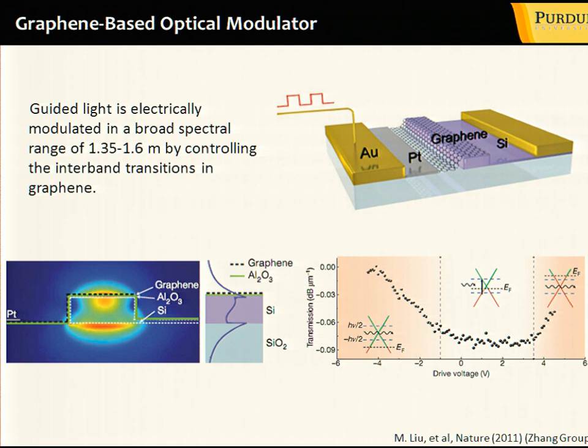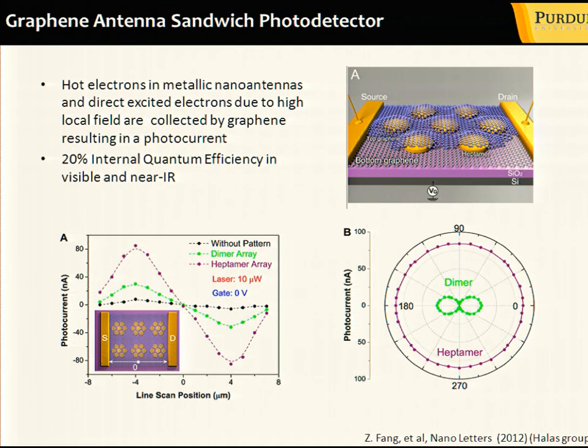Many structures I'm going to show will be using graphene, this wonderful material which has been introduced to the field by Novoselov and Geim, who won the Nobel Prize for this. It really brings lots of functionality. In this case, if you place a graphene sheet on top of a silicon photonic waveguide and change the voltage, you basically move the Fermi level and you could keep it close to the Dirac point. In this case, of course, you have strong interband transition, which means there would be absorption and your transmission goes down. If the voltage is such that the Fermi level goes away from the Dirac point, then there is no absorption and transmission increases. So you could do it very fast and it works as a very efficient and fast optical modulator.